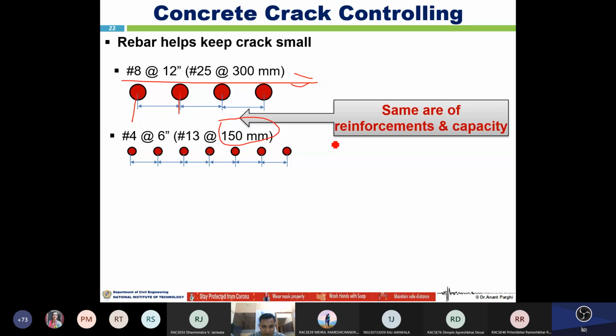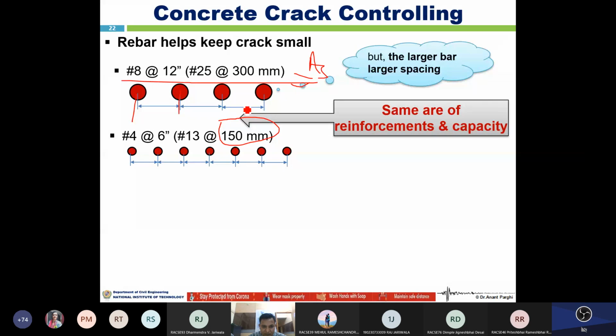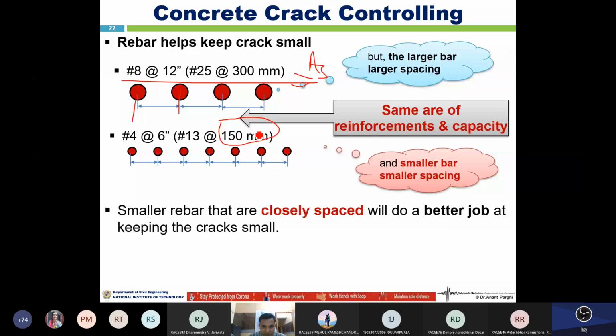Here the area of the reinforcement and the capacity are the same in both sections, but you have reduced the bar diameter and the spacing. Larger bar means larger spacing, but smaller bar means smaller spacing, so the rebar will help to close this space. The rebar will do a better job of keeping the cracks small. Smaller rebar reduces crack width by about 50% in a concrete structure. This is the main thing, so during structural design we have to take care so that we can control it.